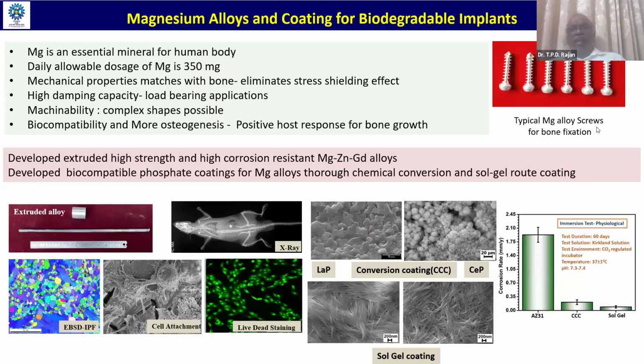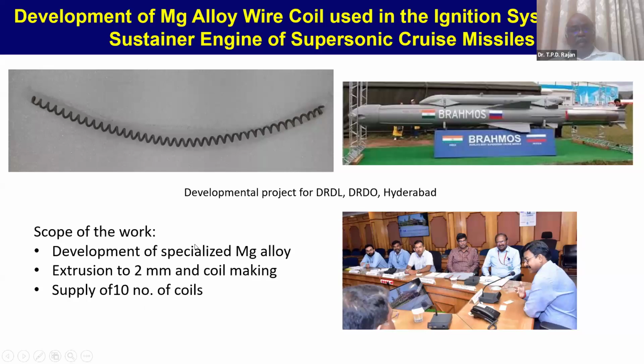So we also collaborate with DRDL and BrahMos on the development of magnesium alloy wire coil, which is again a rare-earth magnesium alloy, used in the igniter system of the sustainer engine of supersonic cruise missiles. Each missile will have almost 4 magnesium coils used in the igniters of the BrahMos. These are being developed using specialized magnesium alloys to a minimum thickness of 2 mm. We have currently supplied 10 coils, and each BrahMos missile will have 4. This development is under test and in progress, and once it is finalized, we will be continuously supplying these coils to BrahMos.